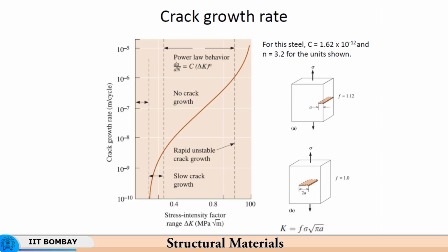So, here there is no crack growth, as sigma changes, then only the k will change. As you go on increasing the delta k value, then the crack starts growing. Now, beyond this point there is a slow crack growth. As a result the stress intensity factor delta k now changes with the increasing length of the crack. So, the crack growth rate also increases, because now you have delta k being determined by a change in the length of the crack. The crack is growing slowly, definitely it grows slowly, but it does grow, right.